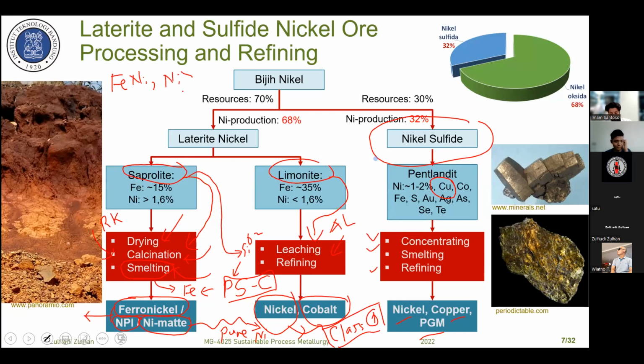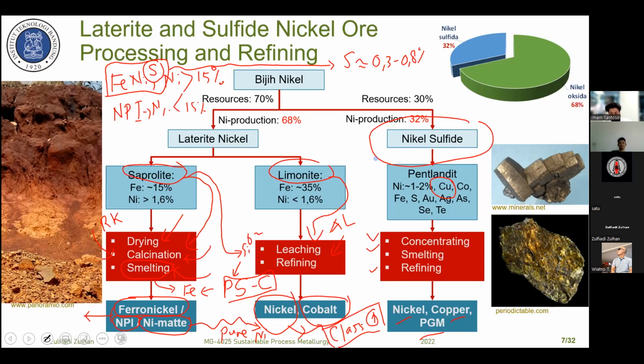We talk about ferronickel. This is the common definition: for ferronickel, the nickel content is more than 15%. And for nickel pig iron, the nickel content is less than 15%. But on the other hand, we should also consider the sulfur content. Usually, if the product is ferronickel, for sure there are crude ferronickel and refined ferronickel, but usually the ferronickel is refined to remove sulfur, from around 0.3 to even 0.8% or even 1% sulfur is removed. There are refining facilities to remove the sulfur content. In the final product, the sulfur content is less than 0.03%. This is the common product of ferronickel.